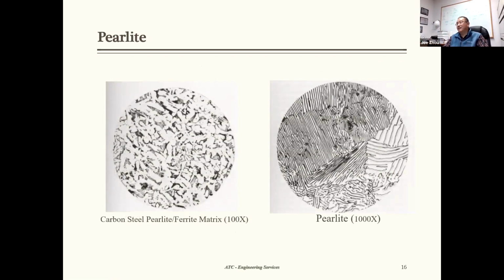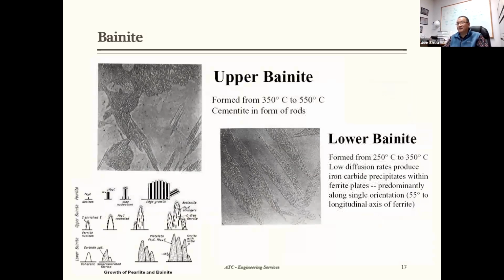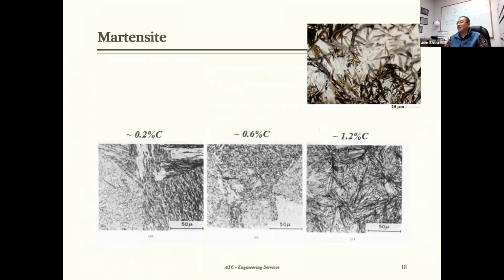So this is a common pearlite, and this is a common bainite. Bainite can be determined as upper bainite or lower bainite, depending on forming temperature. Forming at 350 to 550 is basically the upper, and below that is the lower bainite. I'm not going to touch that. Martensite appearance is significantly influenced by the carbon content. You can see in the bottom three pictures, going from 0.2 to 0.6 to 1.2, the martensite changes its lath structure. The one in the upper corner is 3.2 carbon, coming from quenching cast iron.